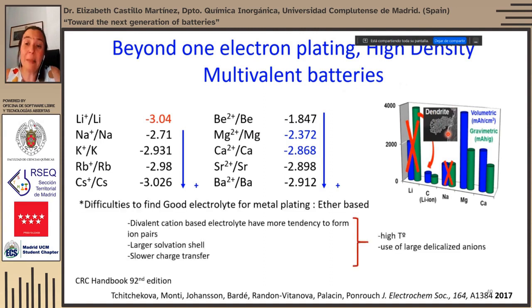An additional advantage is that when these metals are plated, dendrites are not formed. The main difficulty, however, is to find a good electrolyte that allows the plating, because we have cations with very large charge densities. I mean, we have a charge of +2. They tend to form ion pairs with their anions in the electrolyte, and also they tend to get very large solvations there. So it is quite complicated for the charge transfer to take place. So the strategies that are being used are to use high temperature, use large delocalized anions, as well as the use of ether-based solvents rather than carbonate solvents.